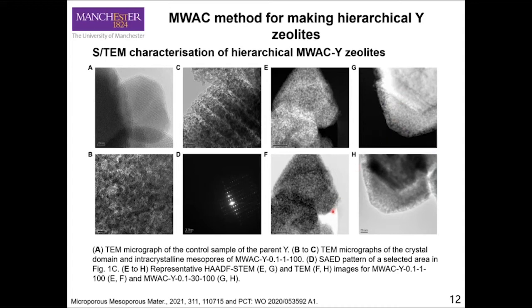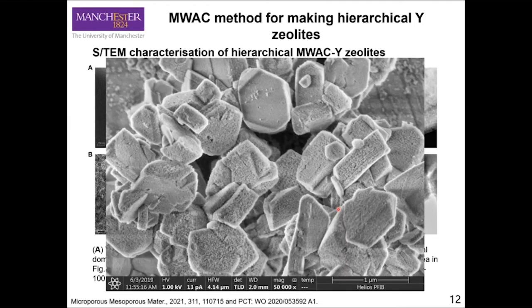We also performed low voltage SEM analysis. Clearly you can see the working distance for doing this is very low, only 2 millimeters. We have to be very careful, and therefore we are able to see clearly after the treatment we developed that there are lots of mesoporous openings on the crystal surface of the Y zeolite. These openings provide the entrance for molecules during the reaction to improve the mass transfer.